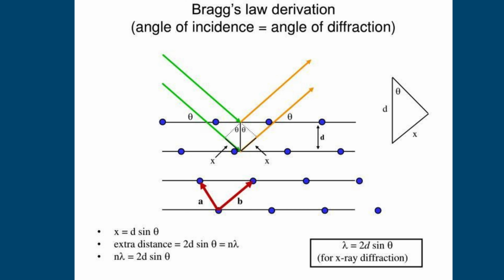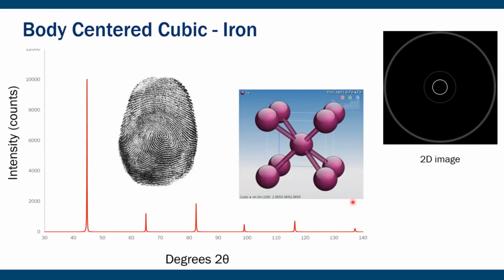nλ = 2d sin θ, where n is the diffraction order, λ is the X-ray wavelength, d is the interplanar spacing, and θ is the diffraction angle. The resulting diffraction pattern acts as a structural fingerprint of the material. Analysis of peak positions reveals lattice spacing and crystal symmetry, while peak intensity and shape provide information regarding crystallinity, grain size, orientation, strain, and defect density.